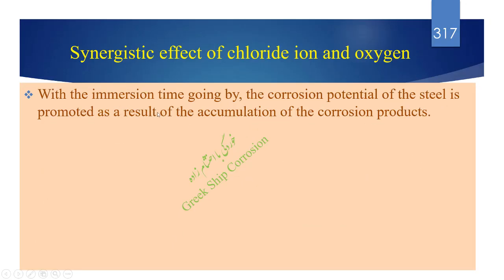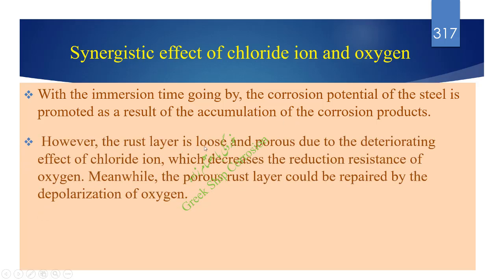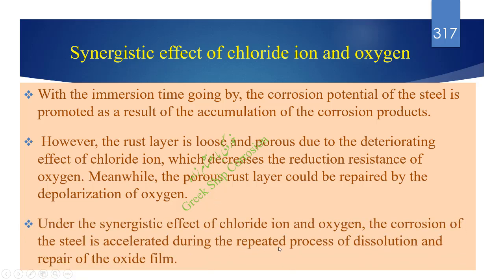With the immersion time going by, the corrosion potential of the steel is promoted as a result of the accumulation of the corrosion products. However, the rust layer is loose and porous due to the deteriorating effect of chloride ion, which decreases the reduction resistance of oxygen. Meanwhile, the porous rust layer could be repaired by the depolarization of oxygen. Under the synergistic effect of chloride ion and oxygen, the corrosion of the steel is accelerated during the repeated process of dissolution and repair of the oxide film.